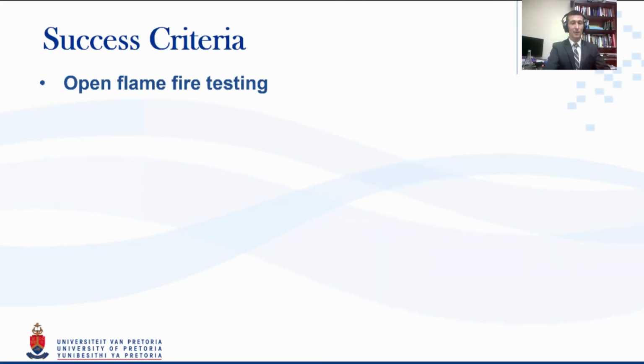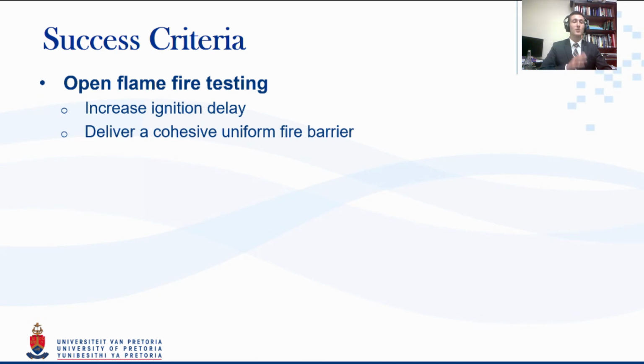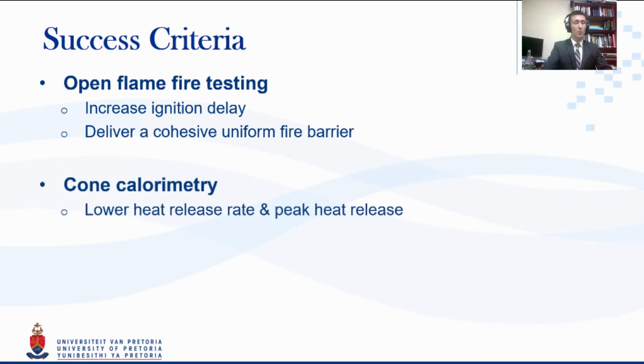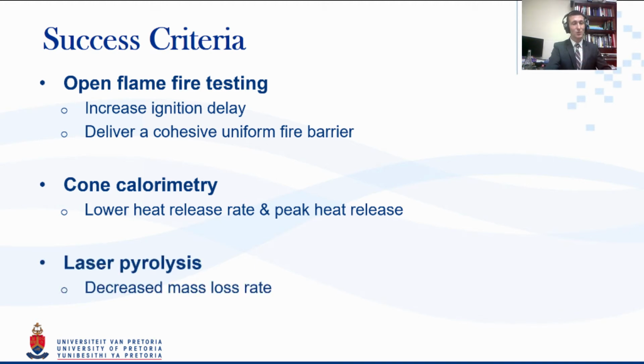We set some success criteria for this. For the open flame test, we wanted to increase our ignition delay, and we wanted to deliver that cohesive, uniform fire barrier from below. For the cone calorimetry, we wanted to have a lower peak heat release, and we wanted the heat release to travel more over a longer period of time, plateauing and making thermally thick behavior in fire testing instead of thermally thin behavior. This allows for a much longer burn cycle, which allows, once again, time to evacuate and time to stop the fire due to intervention.